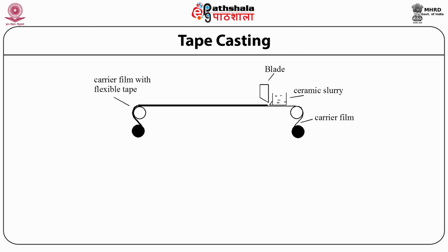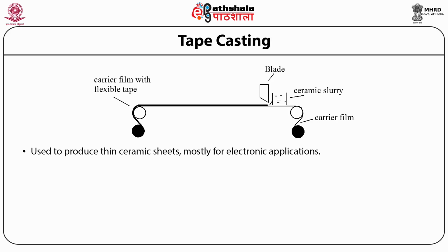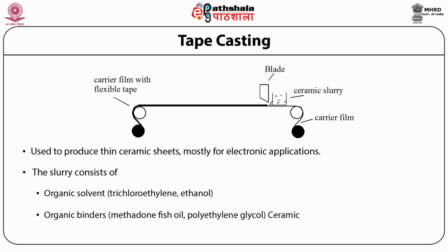The tape casting process is used to produce thin, meaning less than 1 millimeter, ceramic sheets. A slurry made in organic solvents like trichloroethylene or ethanol, and containing substantial amounts of organic binders, for example menhaden fish oil, polyethylene glycol, etc., is poured over a flat surface, and a sharp blade with a small clearance positioned over the surface is moved along the surface, which is seen in this figure.